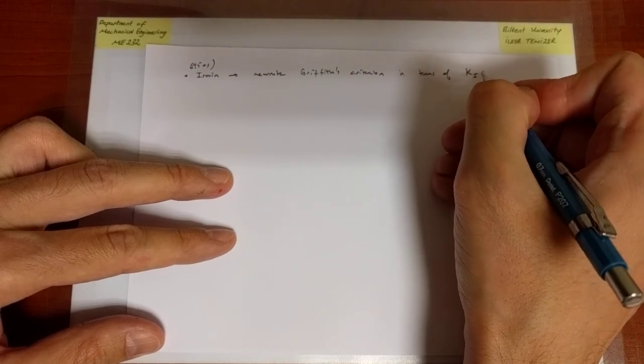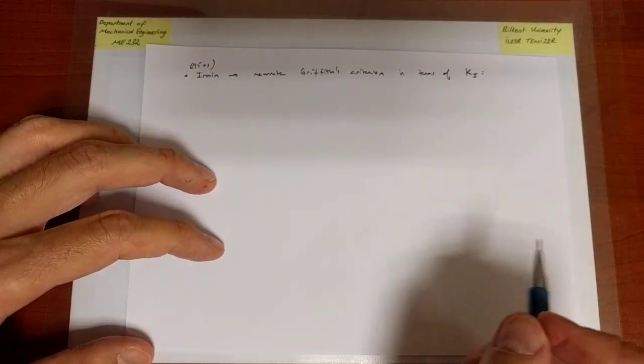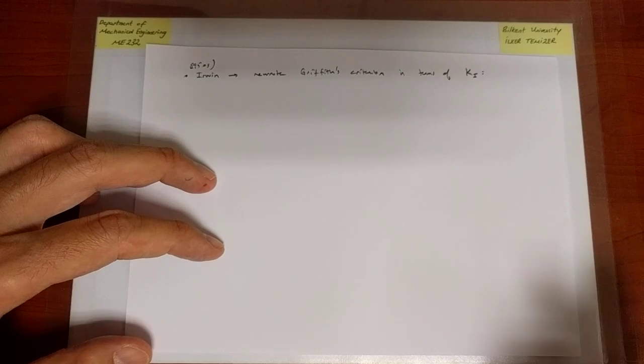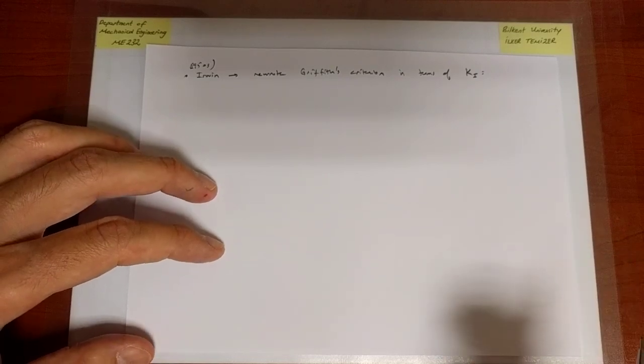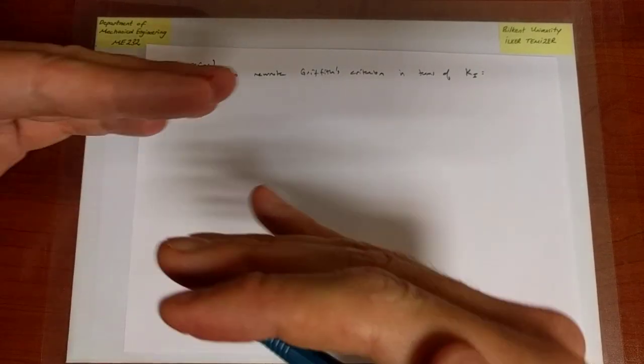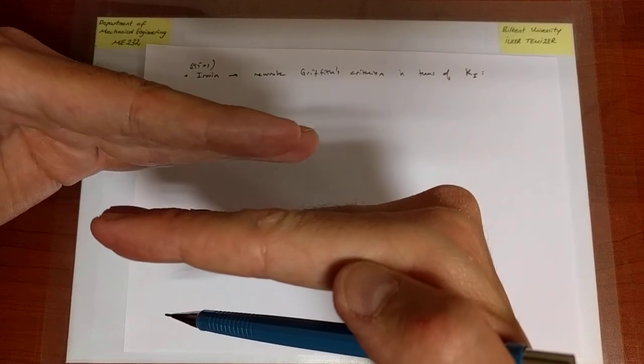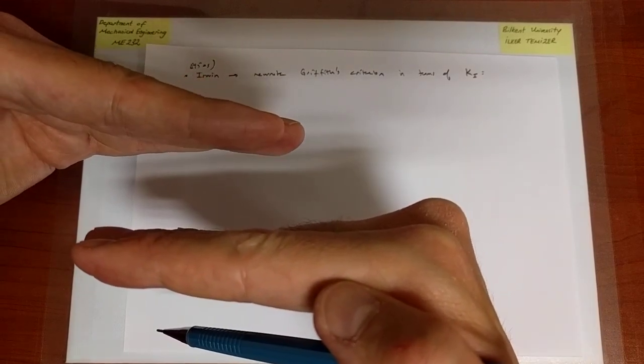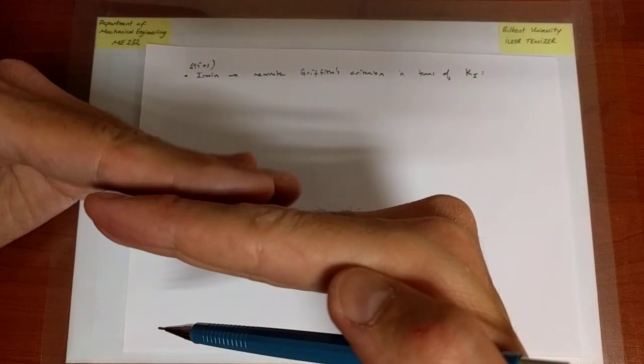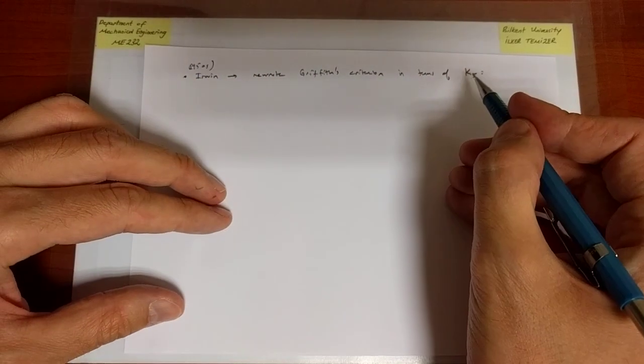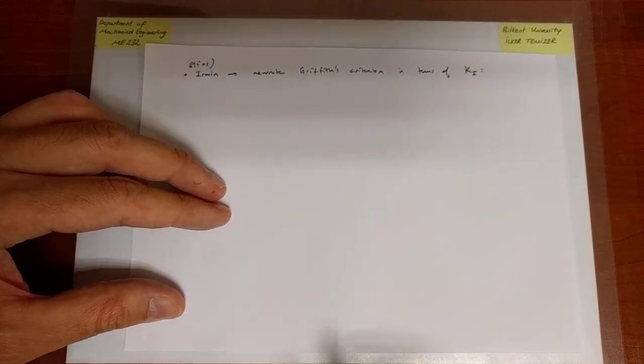K1. So I'm saying K1 because the experiment that we just did had to do with a plate with a crack, and when I pull on the crack, the surfaces of the crack move apart from each other, just like in the peeling off of the tape. So that's an opening mode, which is K1.